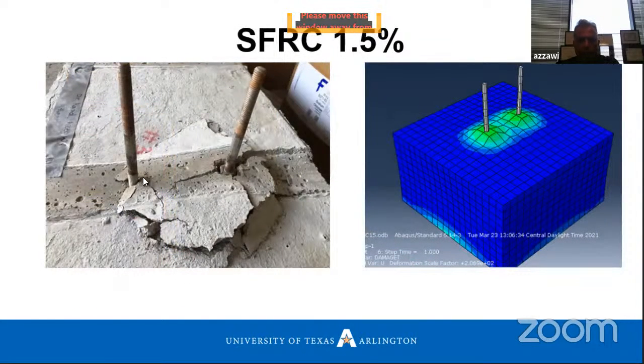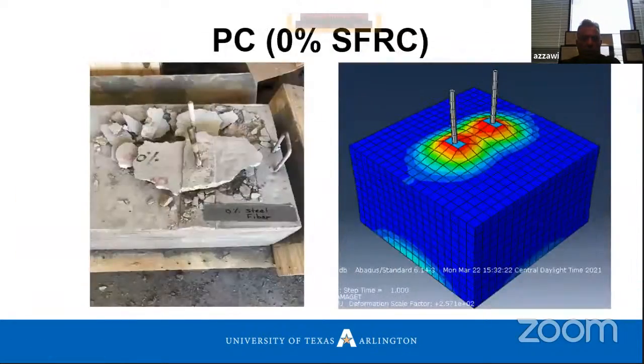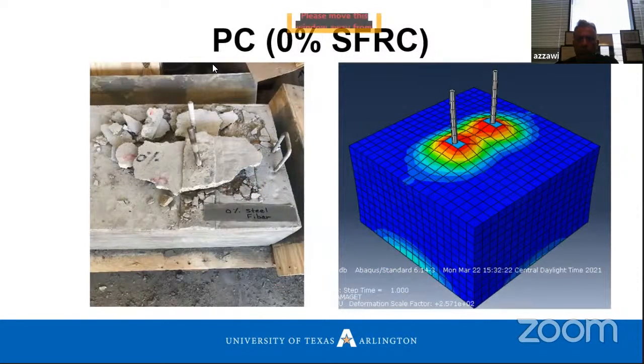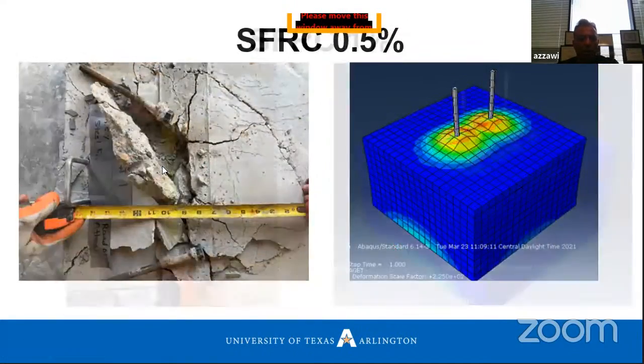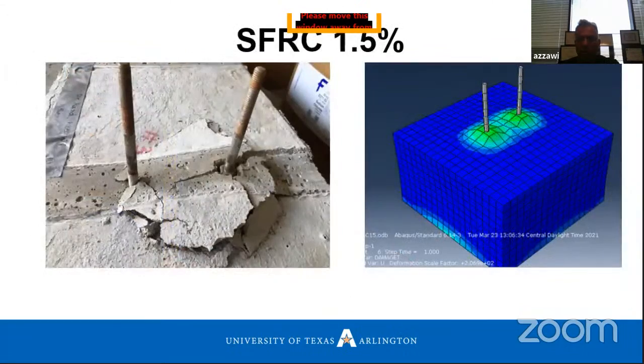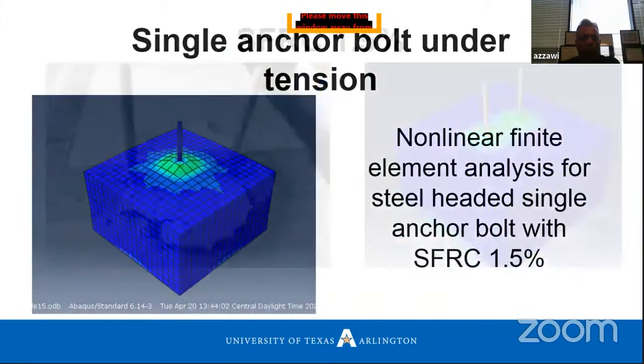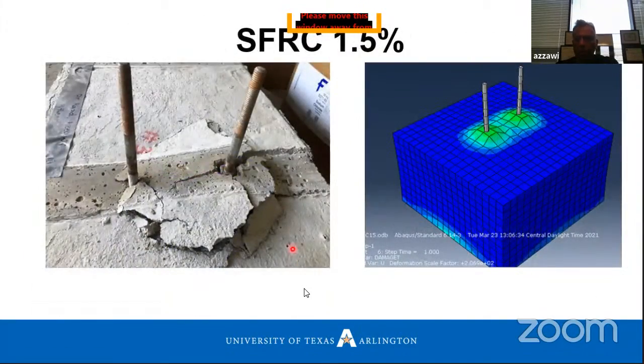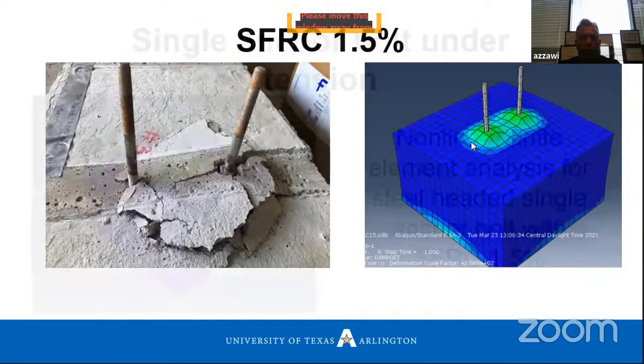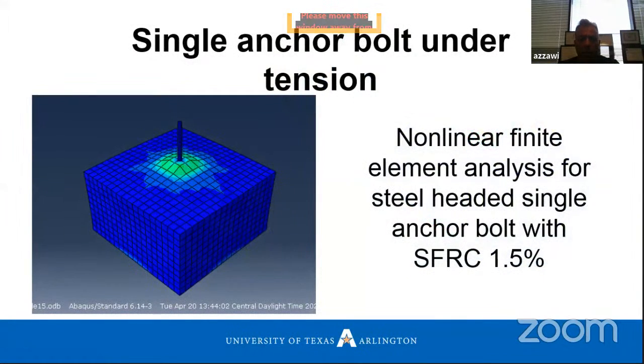For 1.5%, this is the failure, and this is the finite element. If we remember the 0% fiber, see how much damage we had. Same bolts, same embedded length, same everything. We just increase the steel fiber. Instead of 0%, we provide 1.5% and see how that improves the performance of the anchor bolt against tensile failure.